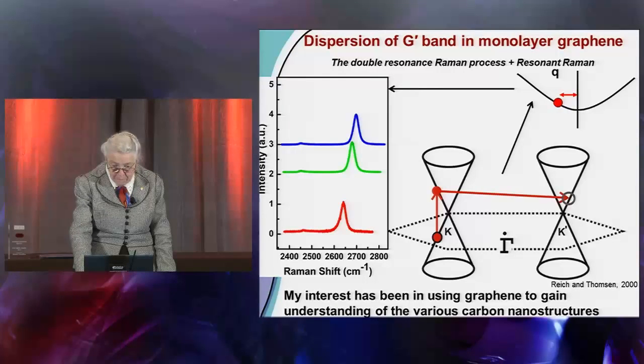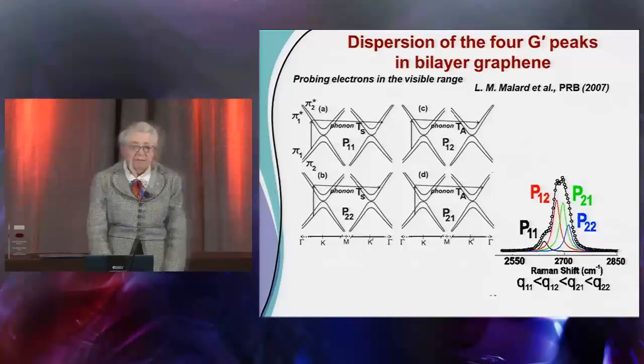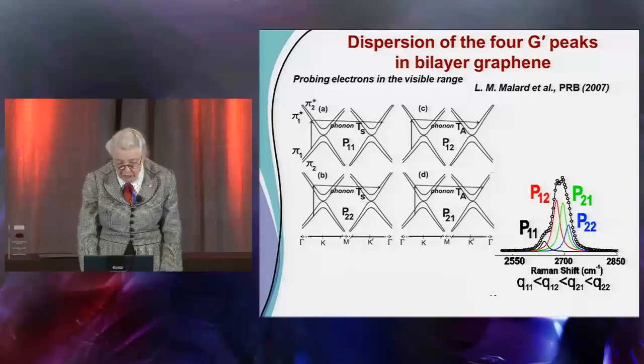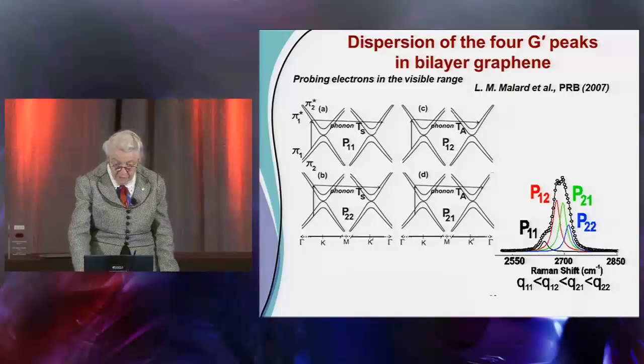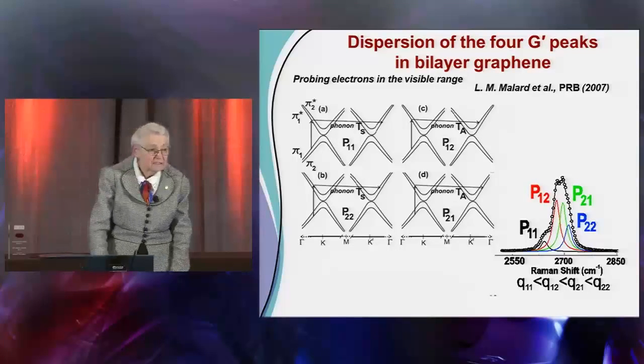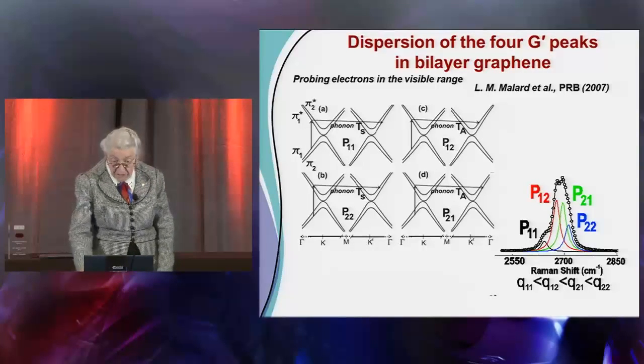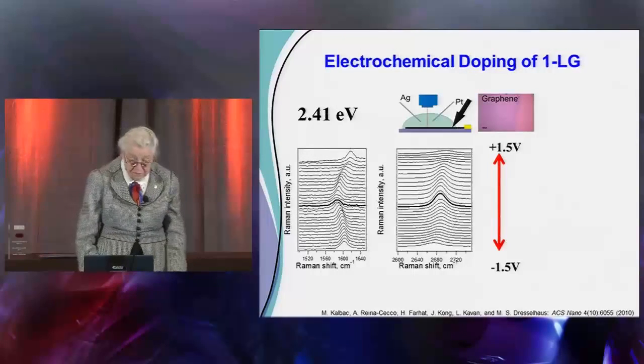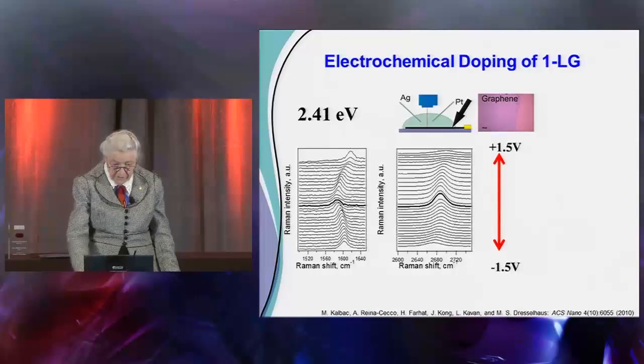And you can't do this on all systems, but it allows you some control on phonons, which has made carbon systems another interesting thing. And they have a very long excited state, the so-called G-band. And that's another unusual thing and gives rise to this extraordinarily large thermal conductivity that we've heard about. One of the prize winners has done important work in that area.